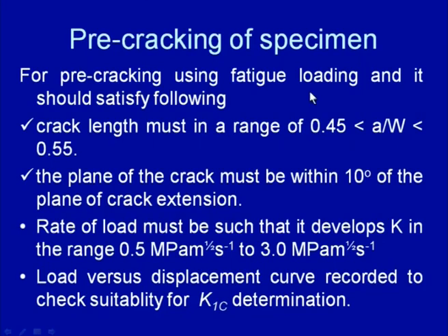Before applying the external load for conducting the fracture toughness test, after machining, a crack is developed by pre-cracking, and for pre-cracking fatigue load is applied. For pre-cracking certain conditions must be kept in mind, like the crack length must be in the range of 0.45 to 0.55, that is the value of A by W.